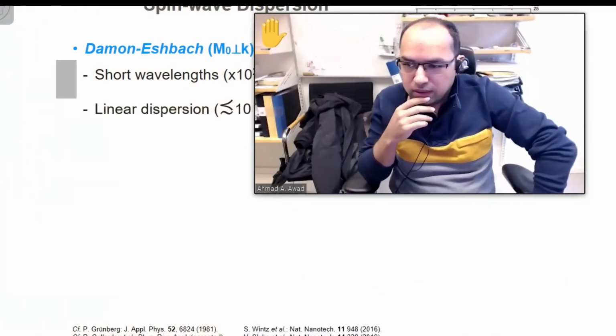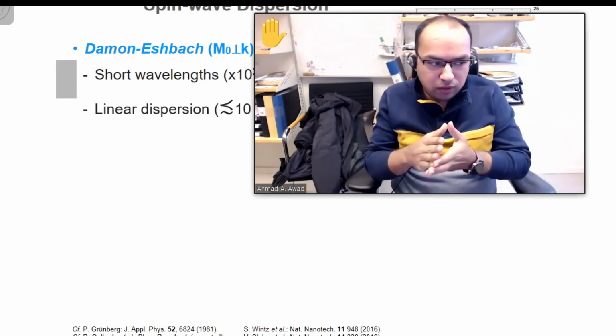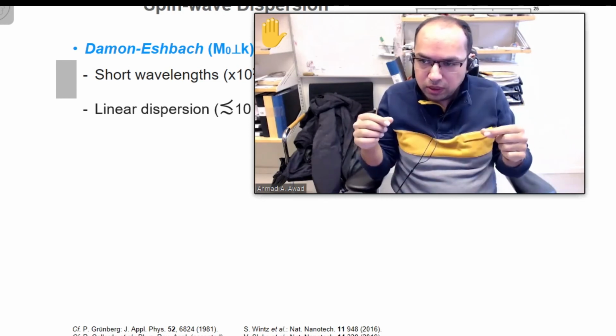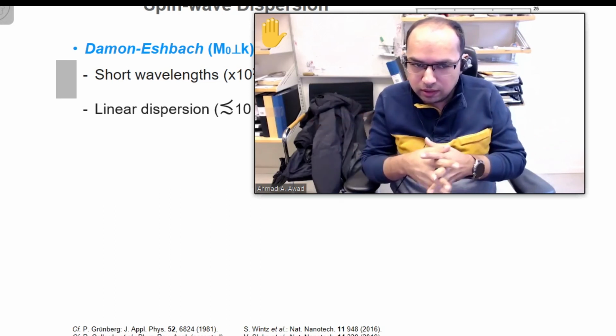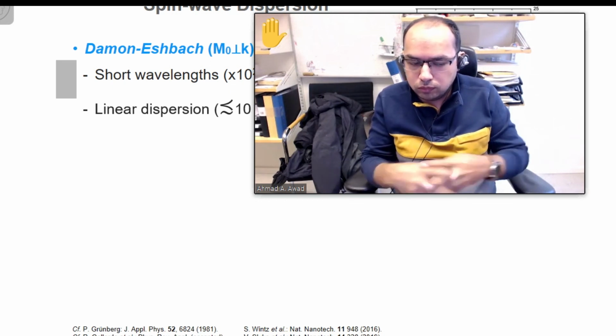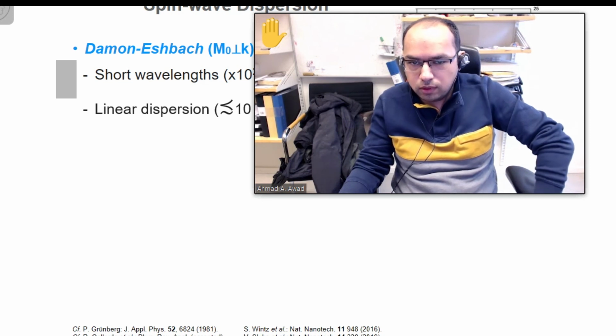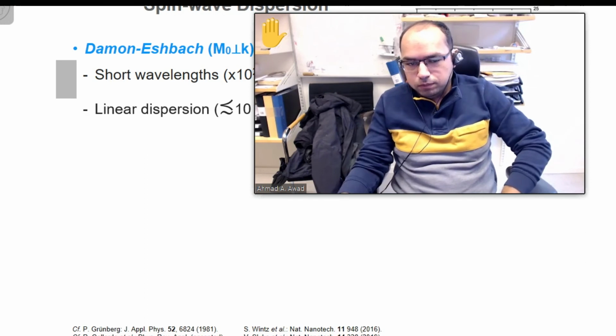Yeah, Sebastian, very nice experiment. For the gallium YIG with this metallic line, the metal is basically a normal metal, it's not like a spin Hall or... No, it's just using the Ørsted field. It's just, I think, copper we used at the time. One could also use spin Hall maybe, but I don't know if that's more efficient because the film was so thick, like 200 nanometers. In principle it should be possible, but we didn't do it.